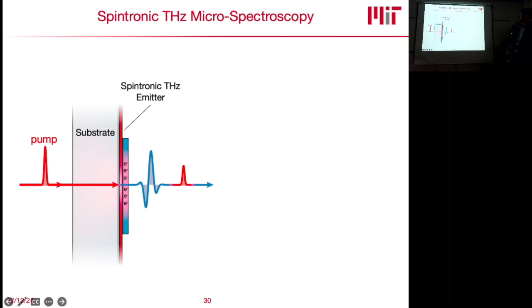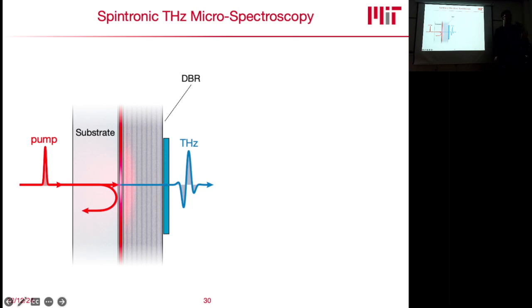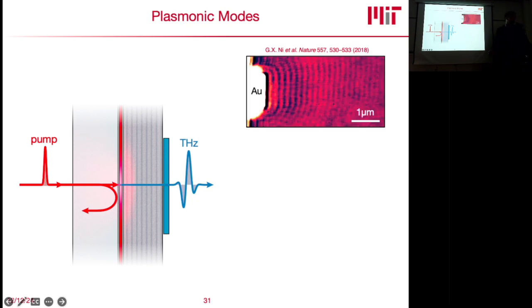The problem with this is, of course, you come in with a higher energy laser beam, you hit this, it excites a lot of terahertz, but the residual beam that is transmitted through the terahertz emitter will also photoexcite your sample. So we would never be able to measure the equilibrium properties. How we solve this is we put in a so-called DBR, a dielectric Bragg reflector, which consists of titanium oxide and silicon oxide, so it's basically just glass. It's perfectly transparent for our terahertz, but highly reflective for our 800 nanometer pump beam. So the 800 nanometer gets reflected back with 99.8% efficiency, and the terahertz beam goes through without any problem. This now allows us to do terahertz spectroscopy of these small samples basically on chip. This is what people like to call it.